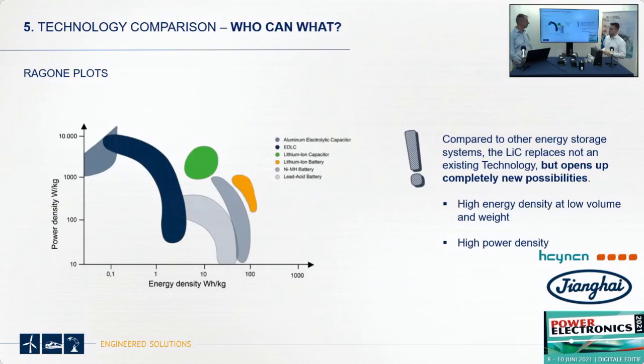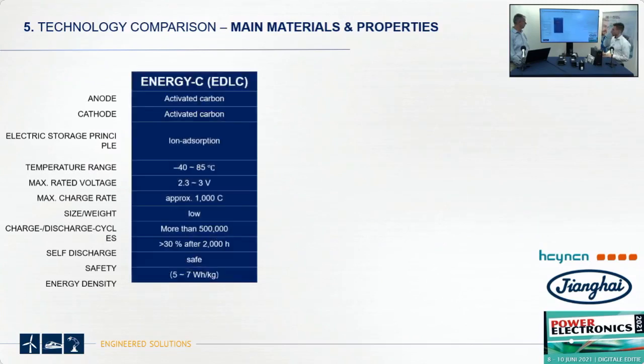I think most of you know the EDLCs, but don't know the lithium-ion technology. And the benefit of the lithium-ion technology is they close the gap between the EDLCs and the battery systems. Here in this free space, there are the lithium-ion capacitors located. In numbers, you have the EDLCs with a very high charging rate, very many cycles, and a limited energy density of 5 to 7 watt-hours per kilogram.